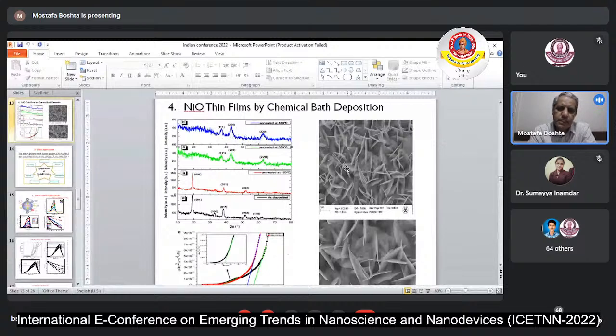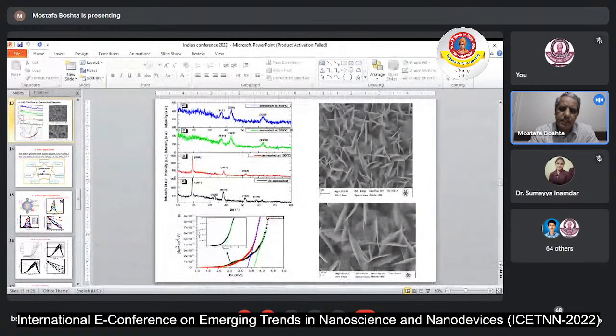If we look at the surface structure of the material by scanning electron microscope, we can see that we have a flake structure which we didn't find with spray pyrolysis. These flakes give us a different surface area and different surface quality, which can give us different applications and different performance for the material. When we use it in the application, as we can see, the flakes are clear here, totally different from the spray pyrolysis which we had before.